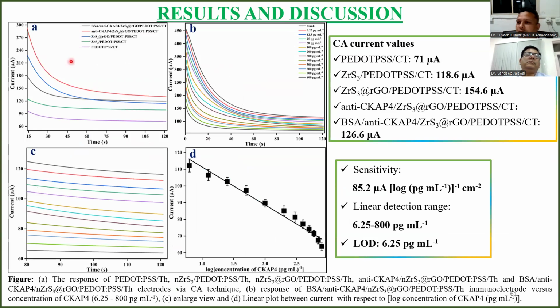In this one, we have obtained some drawbacks when we are talking about the thread base. Here DPV, CV and impedance will not work. Here only the chronoamperometry technique can work. We have not obtained results when using cyclic voltammetry, differential pulse voltammetry, and impedance spectroscopy. But when we did it through chronoamperometry, definitely we got some good results,